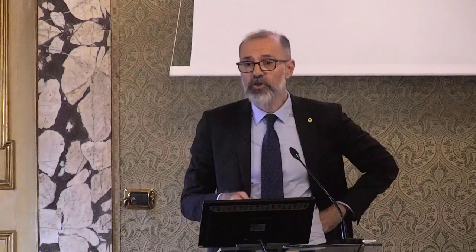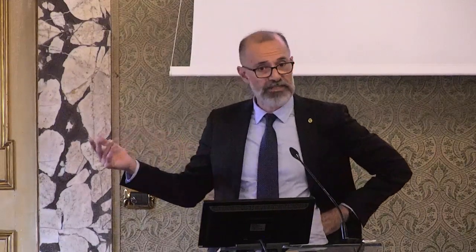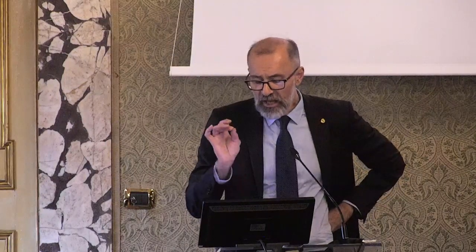Not a single color pigment used in this print was available in Japan traditionally. Prussian blue of the sky arrived in Japan 60 years before this print was made. Pink, it's eosin. The print dates 1881, eosin was synthesized in Europe in 1871. The light red is cochineal carmine. It came from Mexico through Cortes and Charles V. It arrived in Japan in 1869. The violet is crystal violet synthesized by Hofmann and Caro in 1865 in Germany.